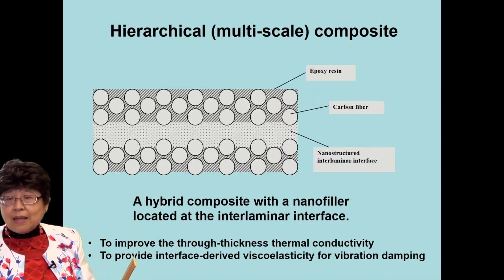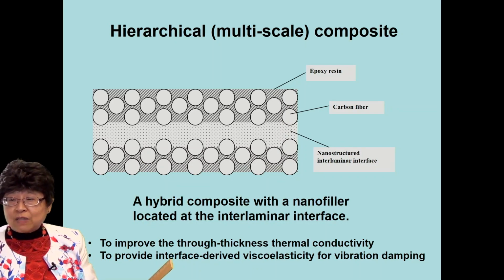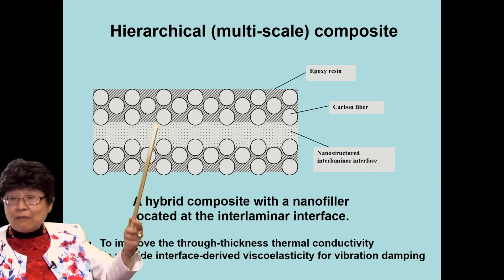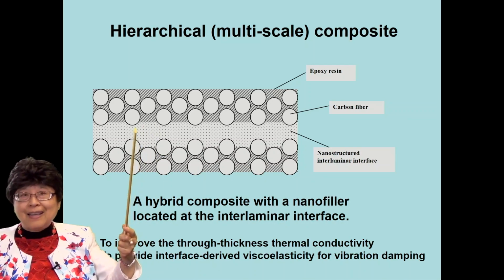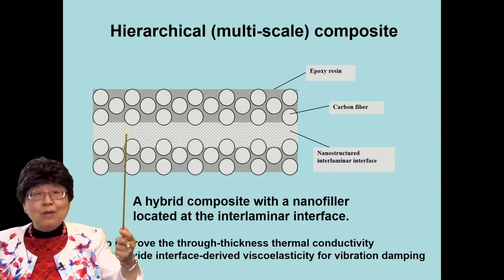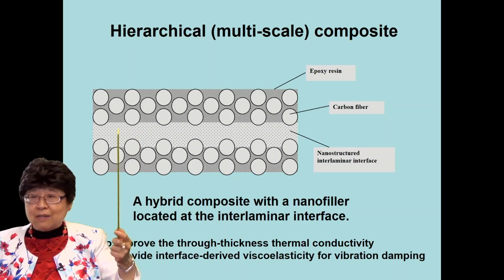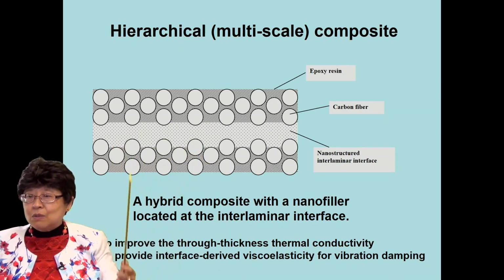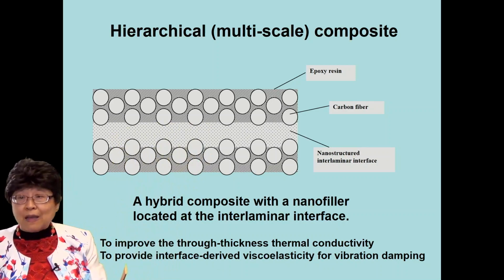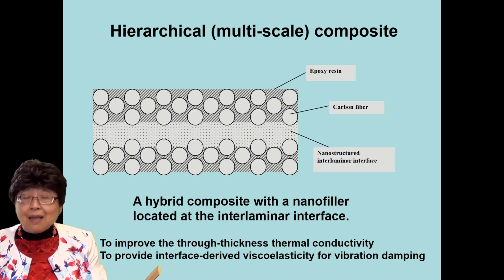Another reason is to improve the interface-derived viscoelasticity. That is, you have nanofiller, so you have interface between the units of the nanofiller and the matrix. And so having plentiful interface there would allow the interface-derived viscoelasticity, thus improving the vibration damping ability of this composite.